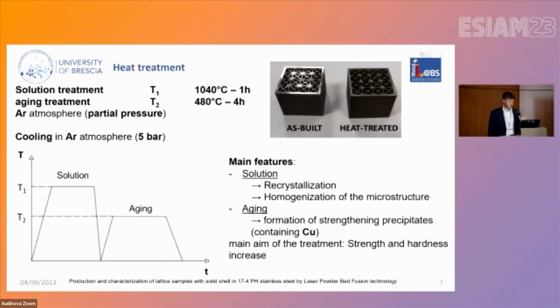The treatment started with a solution treatment at T1 of 1040 degrees for 1 hour, followed by an aging treatment at T2 of 480 degrees for 4 hours. This is conducted in argon atmosphere, also the cooling, to avoid oxidation of the sample as much as possible. The main purpose of the solution treatment was the recrystallization and homogenization of the microstructure, as is widely explained in the literature, and aging was for the formation of strengthening precipitates, in particular copper-containing precipitates. The main aim of the treatment was, in fact, to increase strength and hardness.